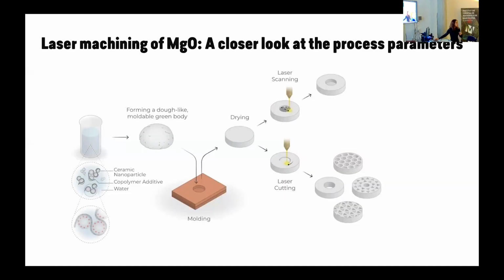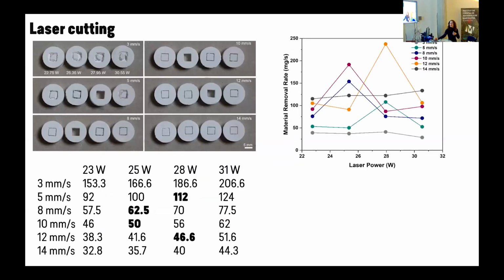Okay, so with magnesium oxide laser machining, this is actually the first processing of magnesium oxide out of a green body through laser machining. I will pass this part. And then what we have done again is the parameterization. We try to figure out what laser speed you should be using, and what power of the laser you should use, in order to get the highest material removal without damaging the material.